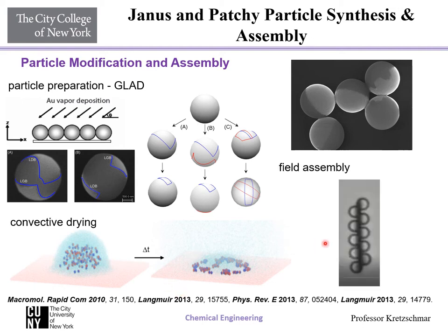In field assembly, we are taking these particles, putting them in an aqueous solution and applying a magnetic field. When these particles are exposed to a magnetic field, you can see that the caps align such that they form this string of particles. And if we now change the electric field that's parallel to the magnetic field here, we get this behavior. The chain expands and contracts and expands and contracts. And so these particles can be quite functional and used in applications, for example, as muscles.